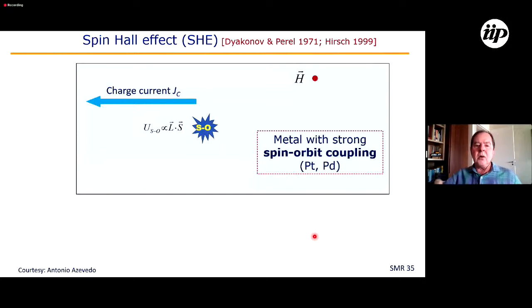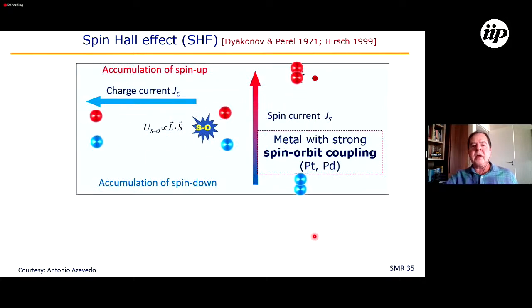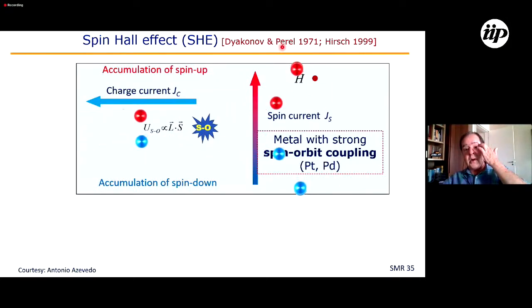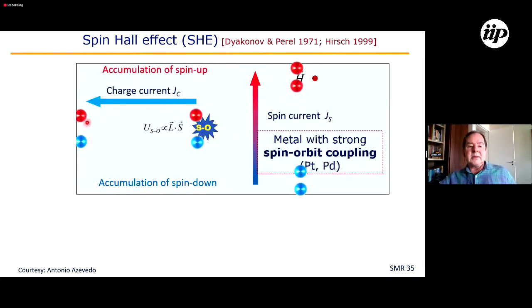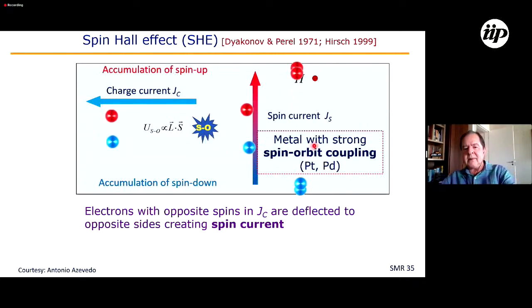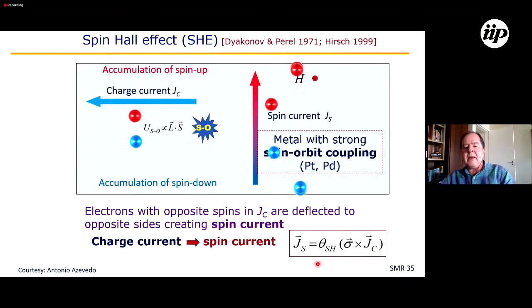involving both currents is the spin Hall effect, which was predicted theoretically by Dyakonov and Perel in 1971 and rediscovered by Jorge Hirsch in 1999. Let's say that we have a charge current in this direction, which means electrons moving to the right. Since electrons have spin up and spin down, if we have scattering, and if the scattering is sensitive to the spin-orbit coupling, electrons with spin up will go up, and electrons with spin down will go down, and then this is a spin current. In this region here, we have a spin current, and the spin current is proportional to the charge current. This is the spin Hall effect predicted by these gentlemen.